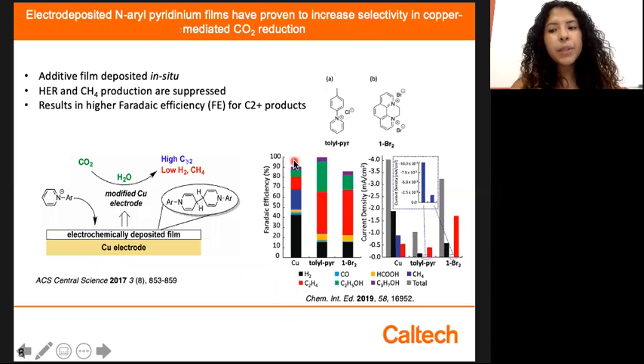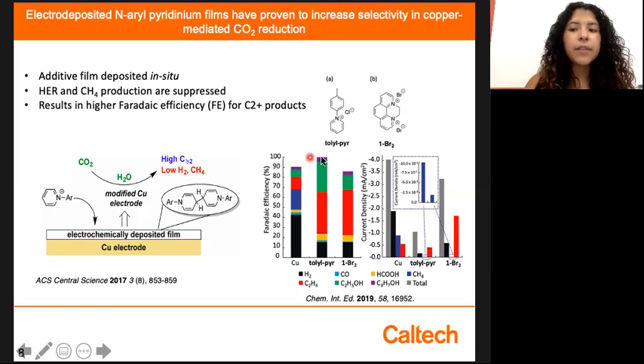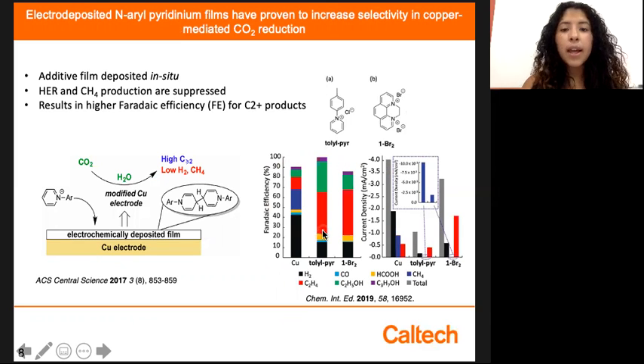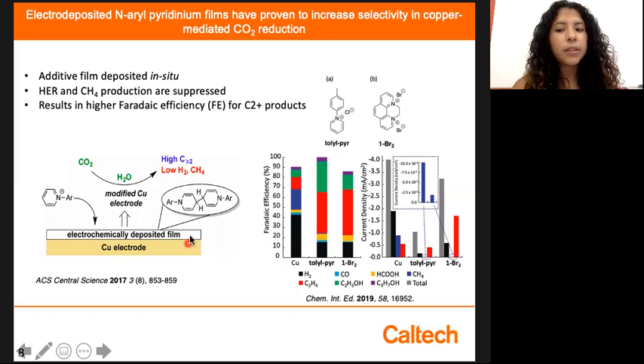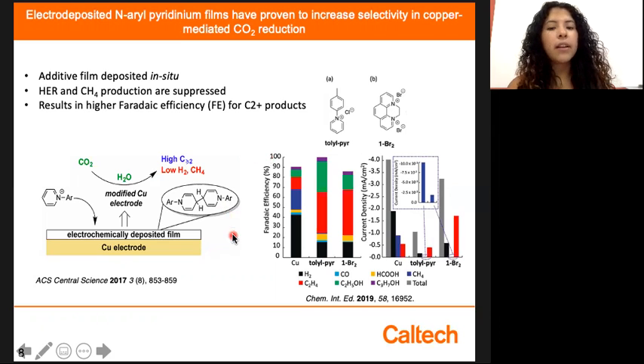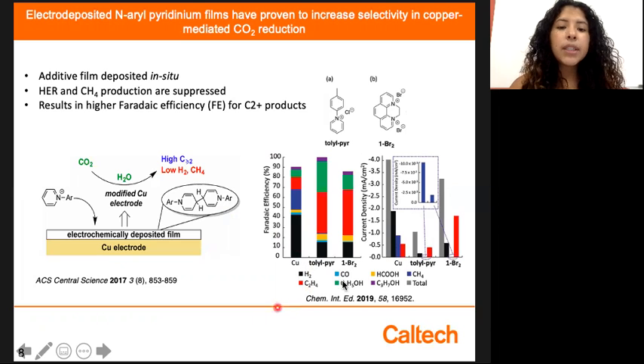But thankfully, the Peters group has done a great amount of research to optimize the selectivity of the copper electrode and found that using N-substituted aryl pyridinium additives that are electrodeposited in situ onto the copper surface has led to great selectivity for C2+ products. This is due to the fact that these hydrophobic organic films are able to suppress HER and methane, leading to higher ethylene Faradaic efficiencies. And as you can see in this figure right here, on a bare copper electrode most of the products being made are side products, but once you use N-tolylpyridinium or N-arylpyridinium additives, you can see that there's a great increase in ethylene production.